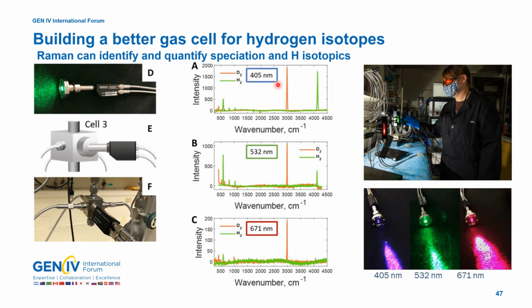In this case, 405 nanometer excitation gives a lot better sensitivity for deuterium and hydrogen measurement. This is the deuterium band here at about 3,000 wave numbers, hydrogen band around 4,000 wave numbers. Very large separation between those two signals. Very nice, easy way to measure this using the Raman technique. As you go down to 532 or 671 nanometer excitation, you can tell that the scale is less sensitive as we go to longer wavelength excitation. And you can also see the ratio between the deuterium and hydrogen isotopes are much different as well. So in this case, we use the 405 nanometer excitation.